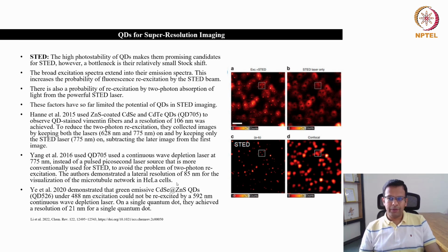Then in another study in 2020, they demonstrated that green emissive CdSe/ZnS quantum dots, that is QD526, under 488 nanometer excitation could not be re-excited by a 592 nanometer continuous wave depletion laser.